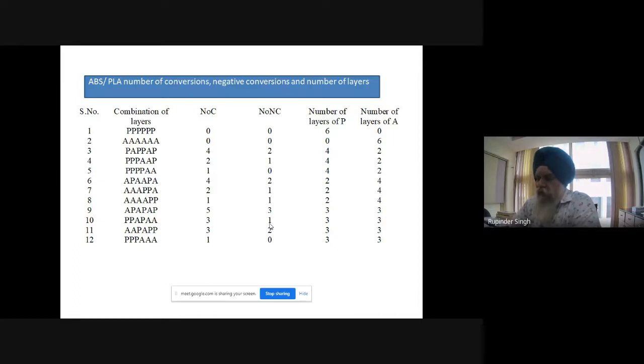If this is the case, and I am interested finally in the strength of the material, the number of negative conversions should be minimum, followed by number of conversions, followed by P and followed by A. That means if you are interested in dual material printing of your substrate from the strength point of view, what we observed in coordination with the experimental data as regards mechanical property and porosity is that A should be more, followed by P, followed by number of conversions, and number of negative conversions should be minimum.